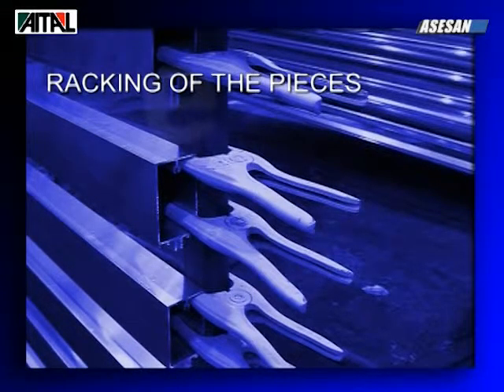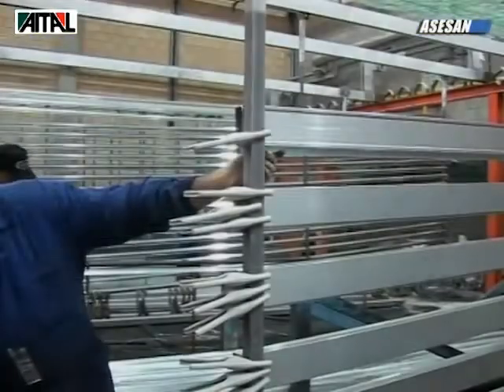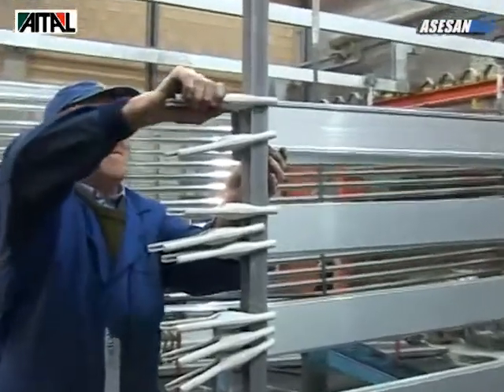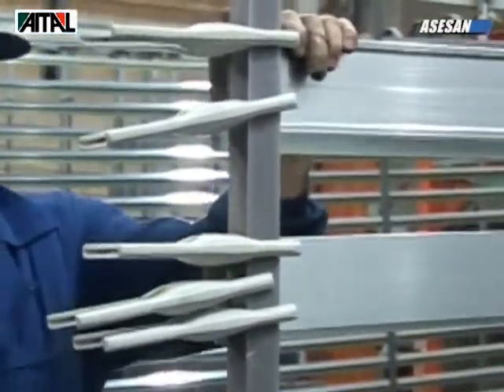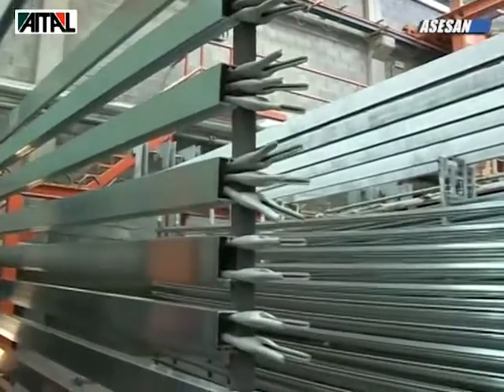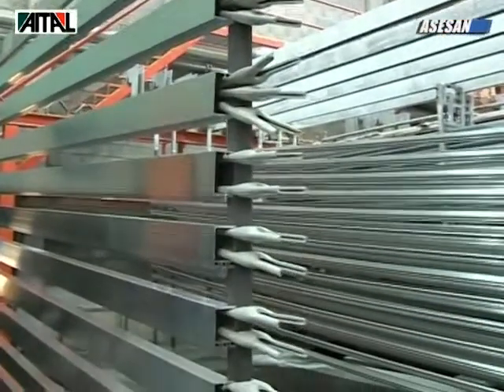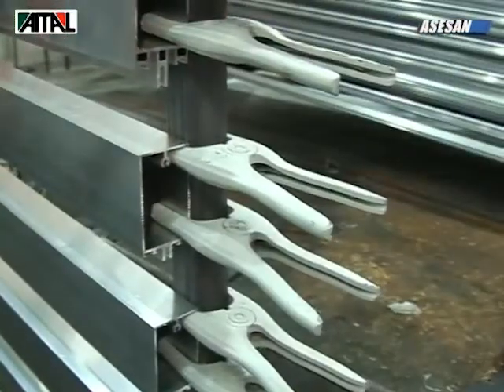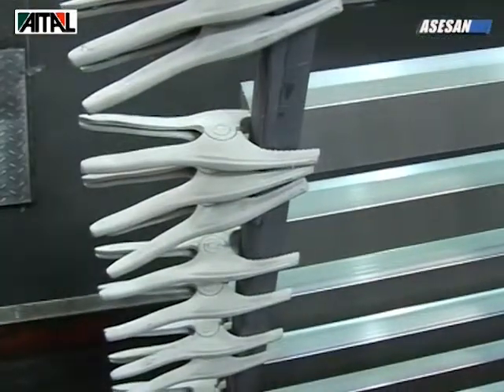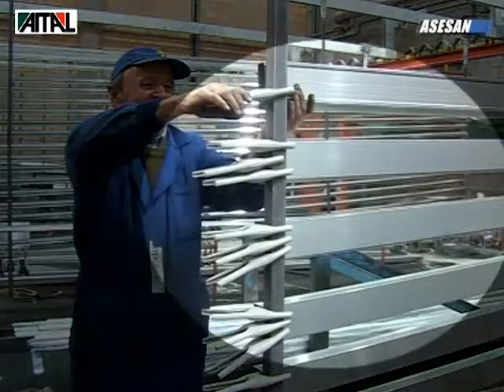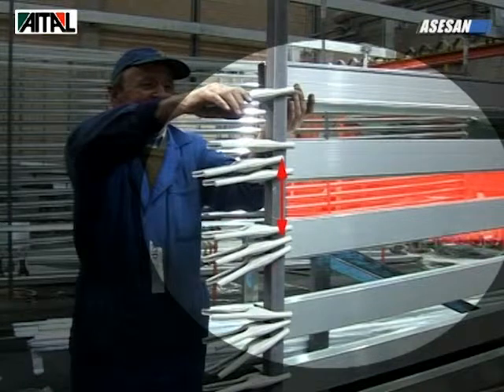Racking the pieces. Anodizing is an electrochemical process. Therefore, it is essential that the pieces make good contact with the support carrying the current. To guarantee uniformity of color, when racking the pieces, a tight contact must be ensured, while maintaining the correct distance between the pieces.